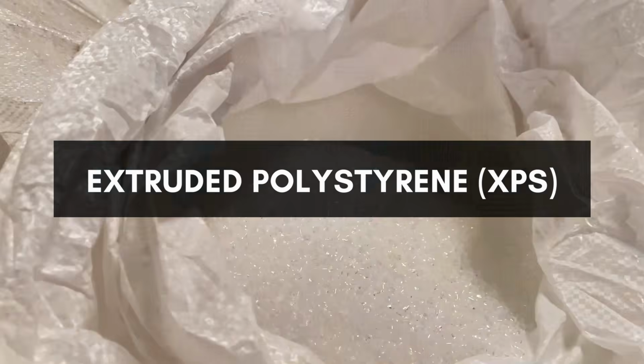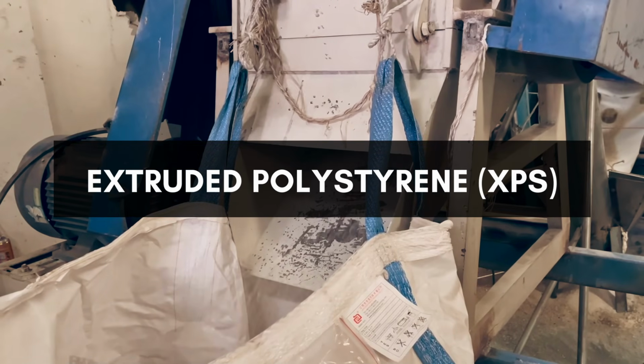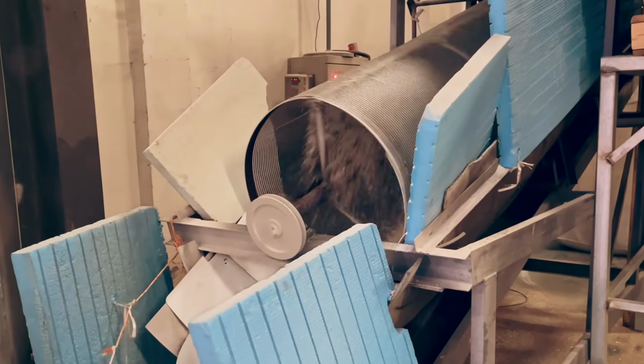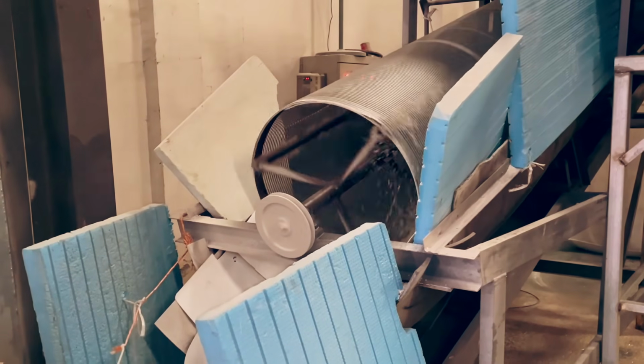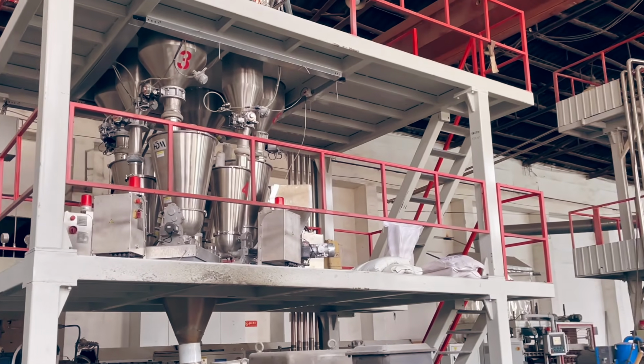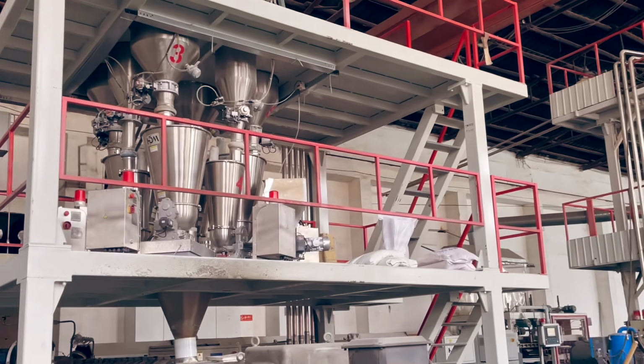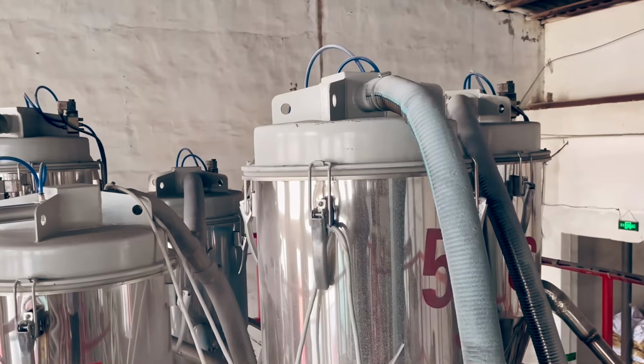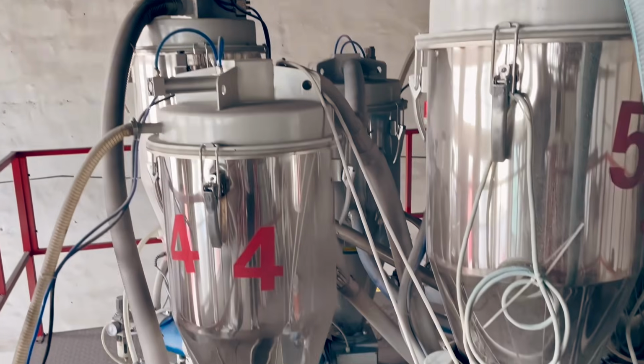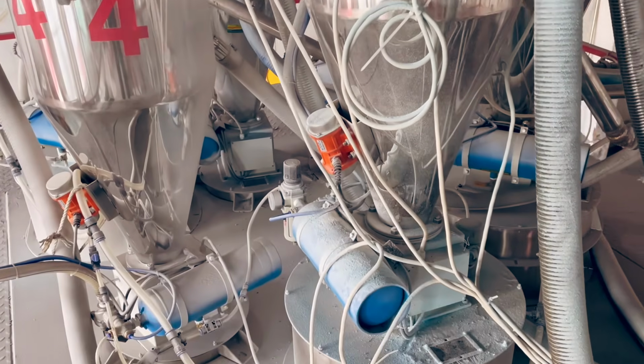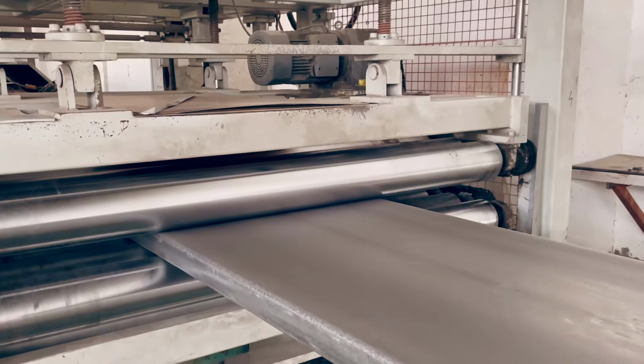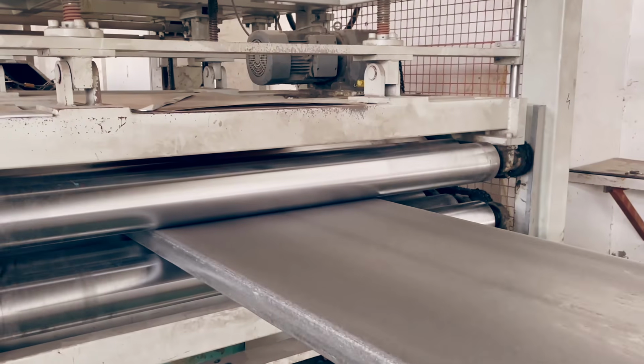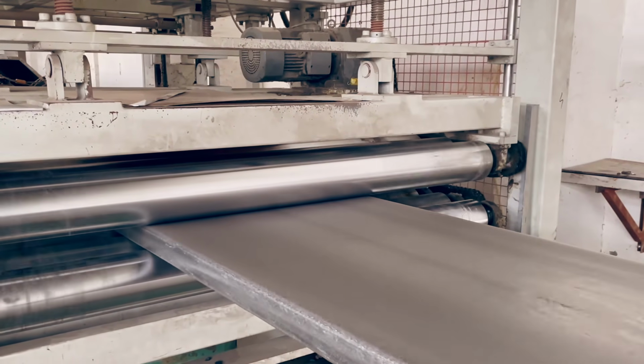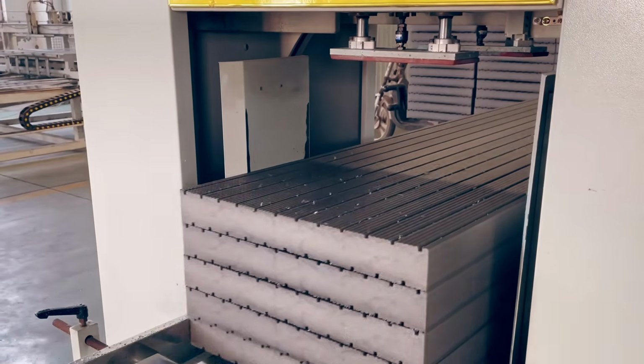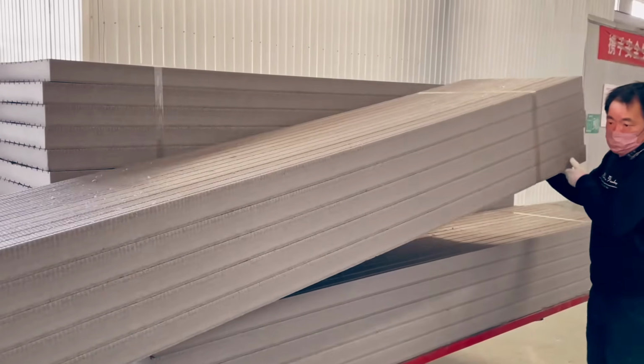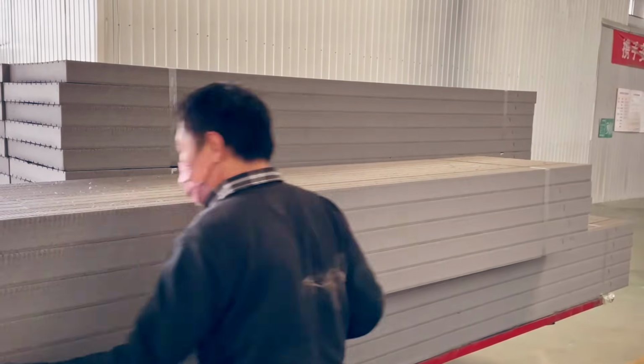Extruded polystyrene, or XPS production, starts by mixing polystyrene pellets with additives, including colorants and flame retardants. This mixture is heated in an extruder until it melts. As this molten mixture is pushed through a shaping tool, a blowing agent within it vaporizes, causing the material to expand into a foam. Once it exits, it cools down, solidifying with a smooth surface. The solid foam is then trimmed to the desired size and, if necessary, given additional treatments for specific applications.